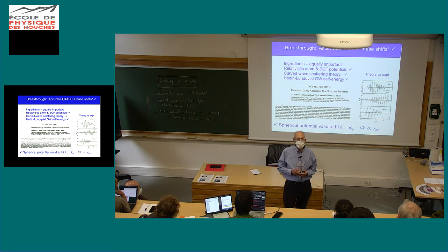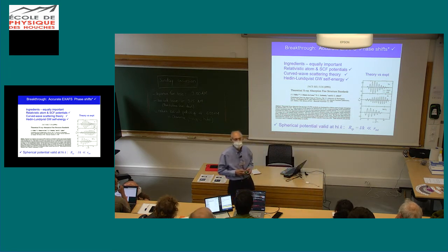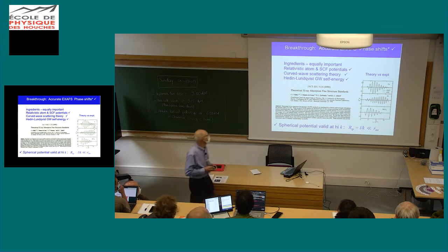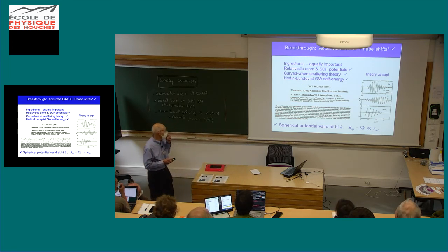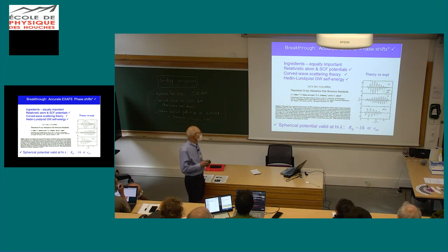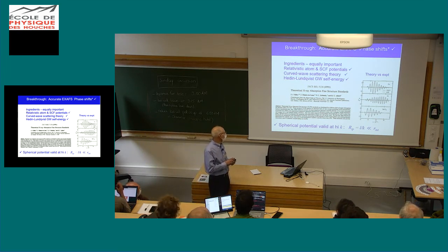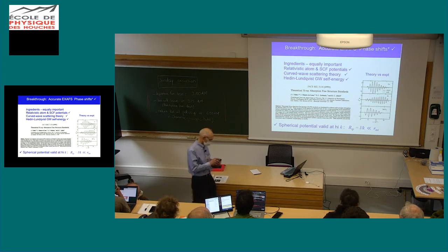So what happens is that after about 20 or 30 eV, the spherical muffin tin works great. And so that's a redeeming feature of doing XAS. So you know, you win some, you lose some. The angular momentum stuff was tough, but at least we didn't have to fuss too much with the full potential, except you have to get the edge right. So you need self-consistency.